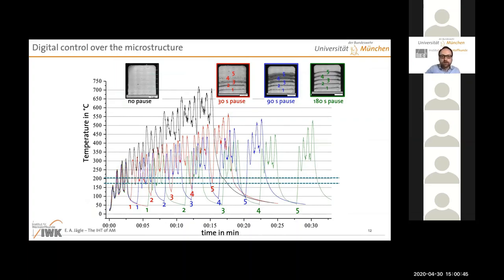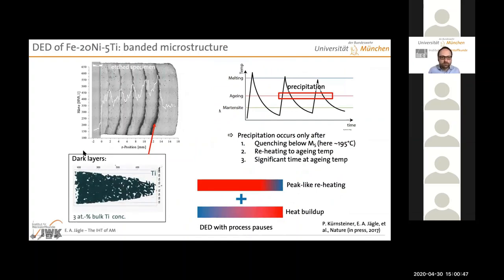Yes, absolutely. I'm sorry, I left a lot of details out in this presentation, but we do look at the microstructure, of course. Here I'm jumping from very coarse to very fine. This is just an etched optical micrograph where you basically only see etched or not etched, and you see a little bit the layers. Hopefully you can see too with the quality that you have. And at the bottom, you see atom probe tomography, on the scale of a few tens of nanometers, showing you the precipitates. But we have, of course, also the intermediate scale.